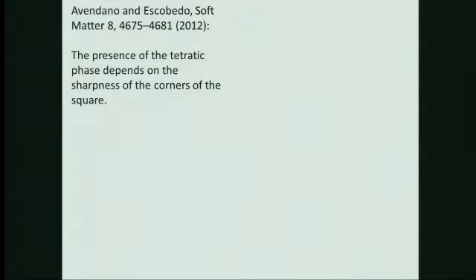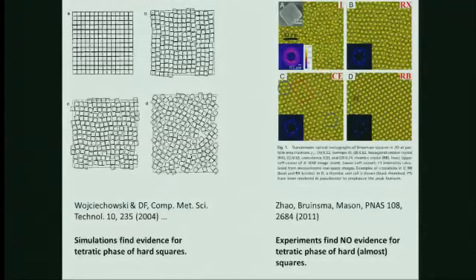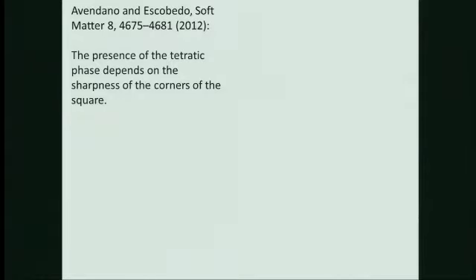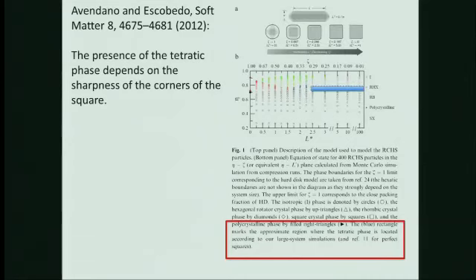Then there was a study by the group of Escobedo at Cornell, and they say, well, actually, if you look very carefully, in the simulation these are by definition mathematical squares, but the experimental particles are actually slightly rounded squares. You think, oh, what difference can it make? But according to Escobedo and Avendano, that actually makes a huge difference. They make these squares by basically putting spherocylinders around a square. The larger the aspect ratio of the spherocylinder, the more it looks like a square. Here you see this is effectively a circle, and this is effectively a perfect square. There are all kinds of phases happening, but this tetratic phase only seems to happen in a regime where you have really very sharp corners. So somewhat surprisingly, this phase is not very robust if you make the particle slightly rounded.